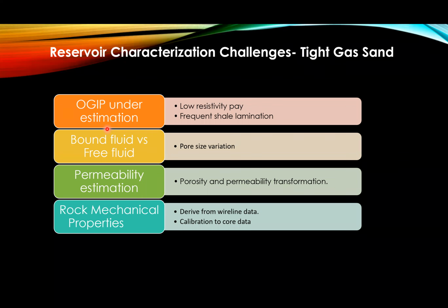And because of the vertical resolution, the entire section, even though the sand might have hydrocarbon and should have shown higher resistivity, is actually masked by the lower resistivity from the clay. So what will happen? If you just derive saturation based on a gas in place estimate, then you will be estimating very low gas in place in those areas, or you may even bypass or discard that section, considering it to be a non-reservoir section without hydrocarbon in it. So that's one big challenge in tight gas sand.